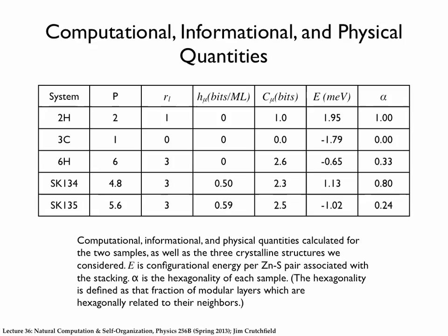One is that from the Epsilon machine, we can calculate physical quantities that you have been aware of. This is the order of the Markov process. And we find that for these reconstructed machines, we had to go to R equals 3, which is third order Markov. We're able to calculate what the stacking entropy is, and we're also able to calculate what the complexity is needed to describe these. And I'll give you some comparison with other structures.